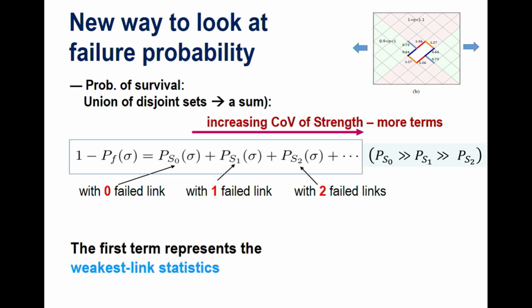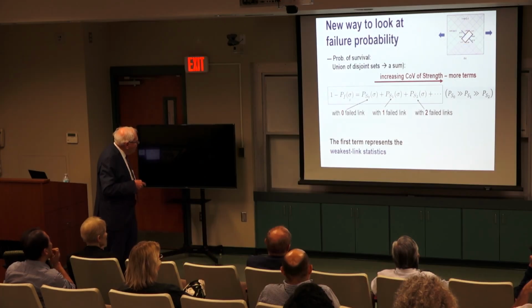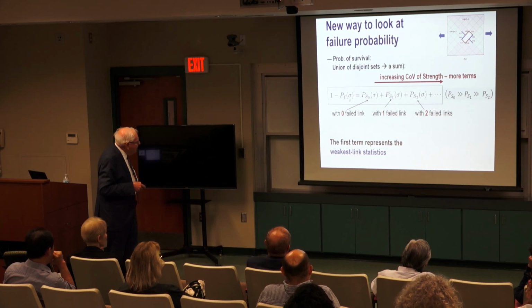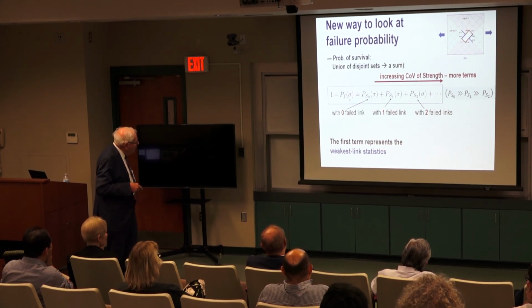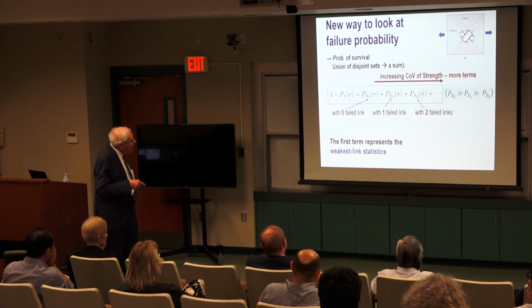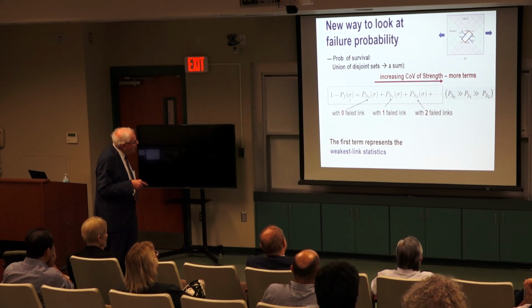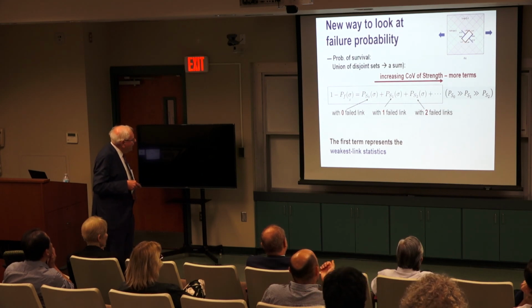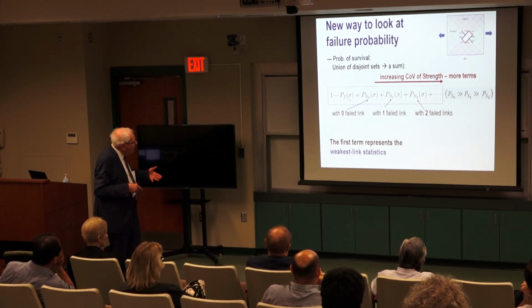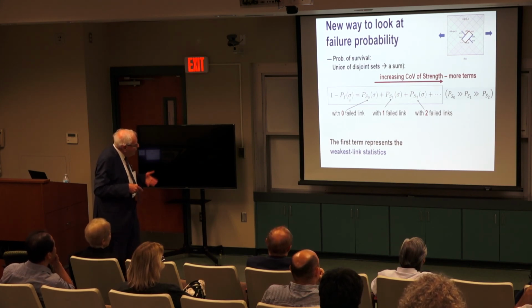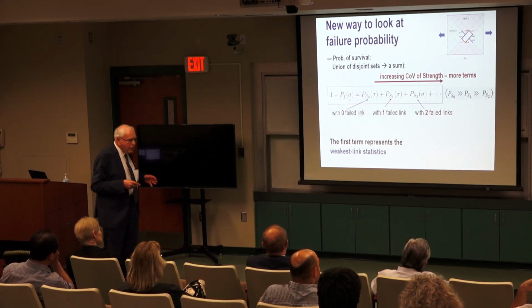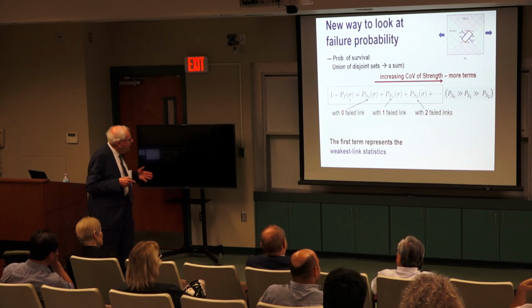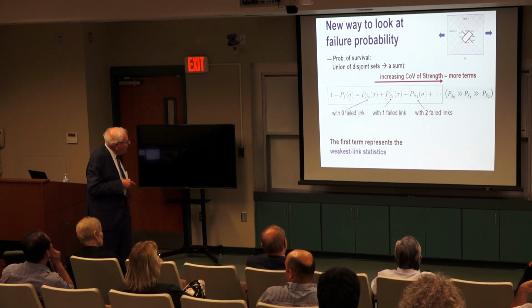Now, how to approach it analytically? So, differently than Weibull distribution or fiber bundle, we consider survival probability, which is 1 minus failure probability, and it would be a sum of a number of terms where this corresponds to survival with zero failed links. It means it fails when the first link fails in the fishnet. One link fails here, and there is a redistribution. This has higher stress, more stress, then it goes to no redistribution of stress. Now then there are cases where one link failed before failure, it means failing as a second link. That's distributions where it survives with two links and fails as a third link. So these are events which are disjoint, independent elements. It's really, in probabilistic terms, a union of disjoint sets. And that proves it must be a sum.